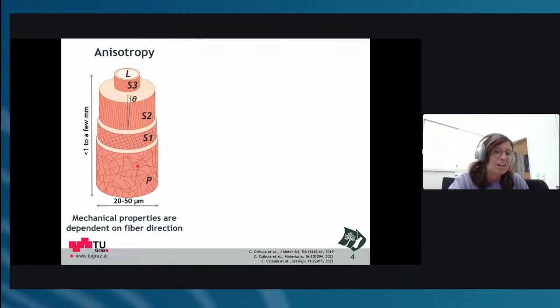You can do a little bit of nano indentation on the transverse side and then play around with methods, but it's very tedious and hard to get really with one mechanical method the full characterization of the anisotropy. And it's also experimentally tedious because it's very error prone. You really need to be on top to make this very clean and smooth, and then it's very little data that you can get out of it. So this anisotropy has been on my way since the PhD studies.